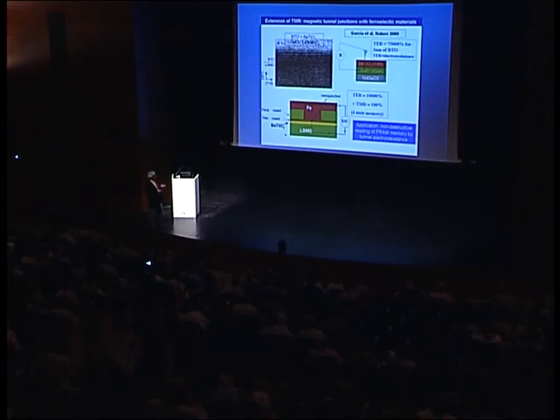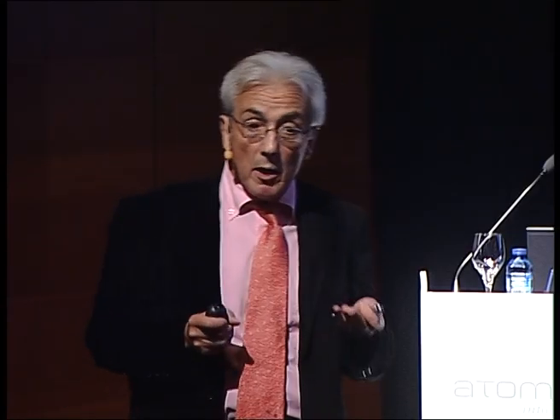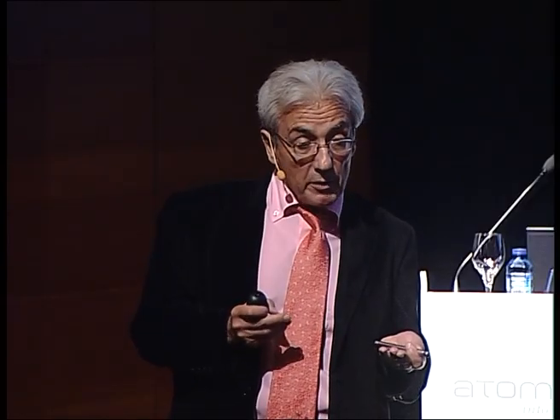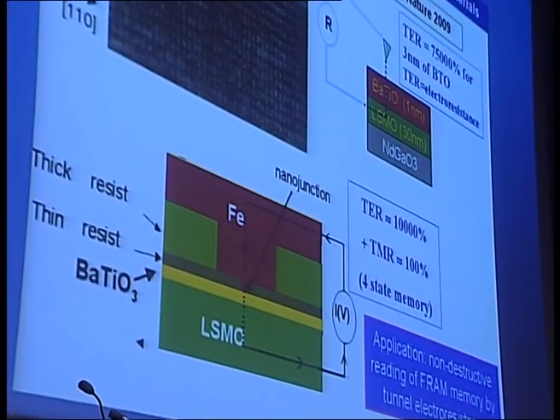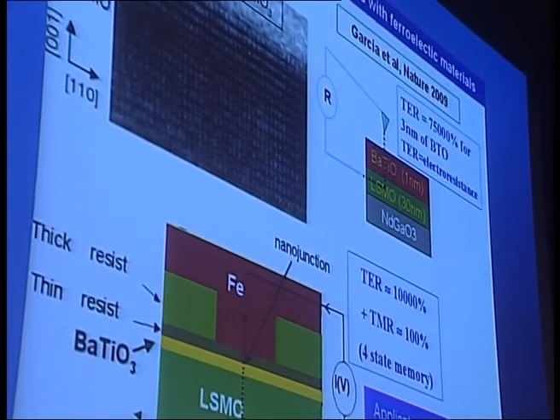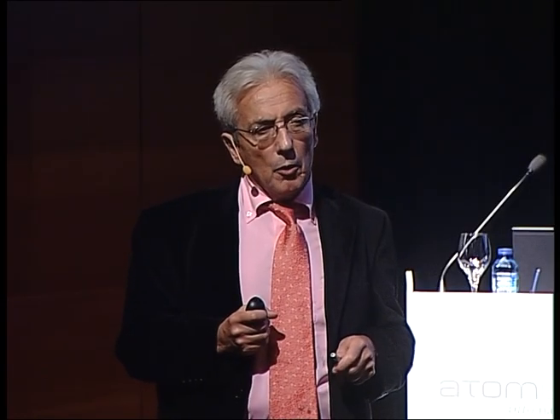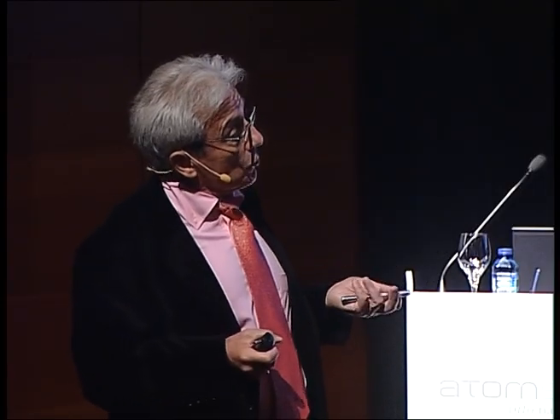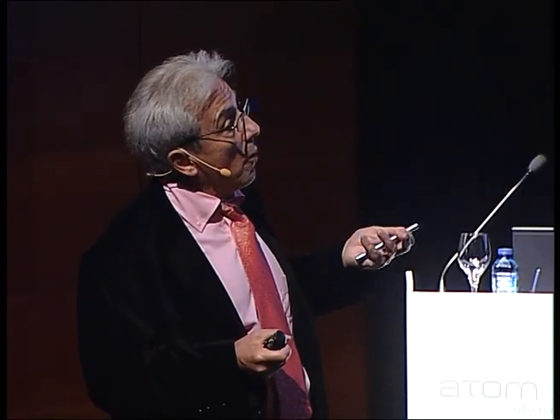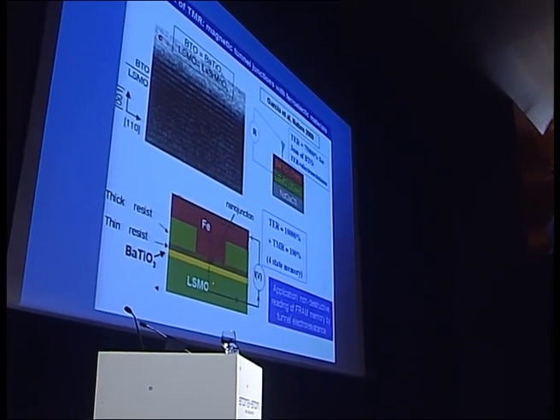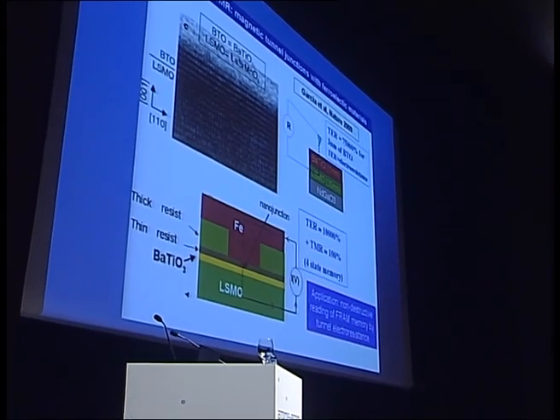So we have obtained tunnel junctions with very high electroresistance. This can be interesting for the FRAM memory. FRAM are memories storing the information in the ferroelectric polarization of a ferroelectric material. And at the moment, this FRAM exists, but the reading is obtained by a capacitance effect. And this is not a very convenient process because this is a destructive reading. And this experiment opened the way to a new type of FRAM memory with a reading by the tunneling electroresistance. One can read the orientation of this layer of BTO by looking simply at the resistivity and at the strong difference between the two orientations of the ferroelectric layer.